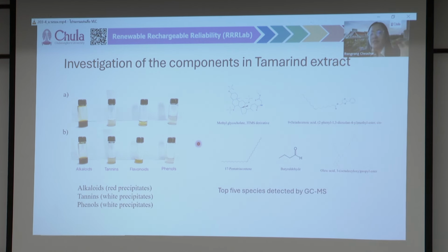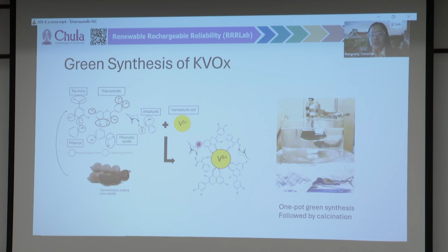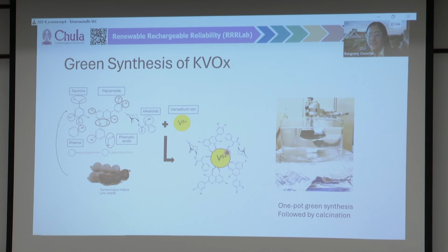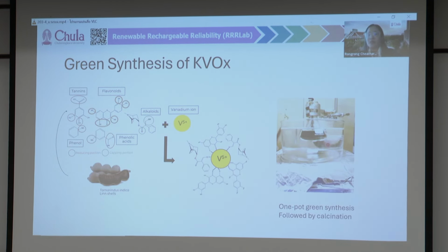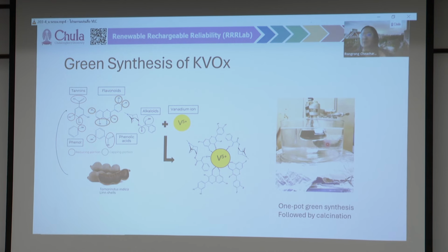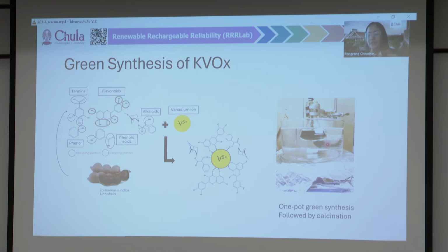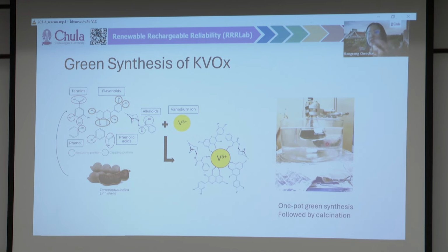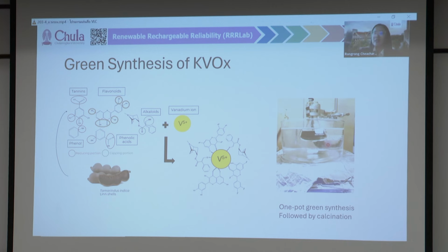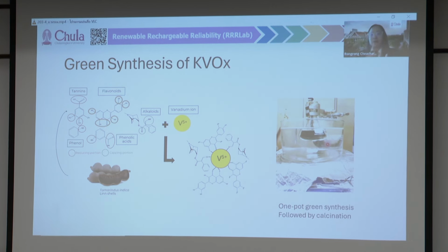So once we have this extract, we do this green synthesis where we put it in an oil bath at a temperature around 100 degrees Celsius, and put in the vanadium precursors, and then we put in the extract and let it stir. Once we get the precipitates out, we take this precipitate and do calcination at a temperature around 500 degrees Celsius.